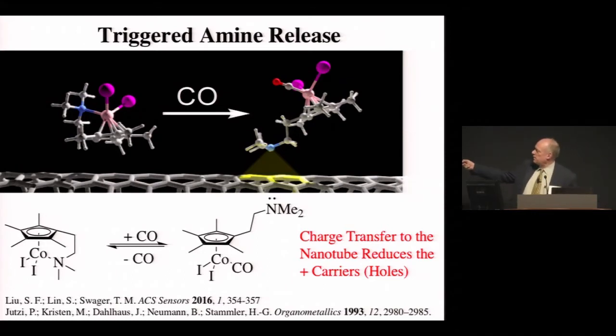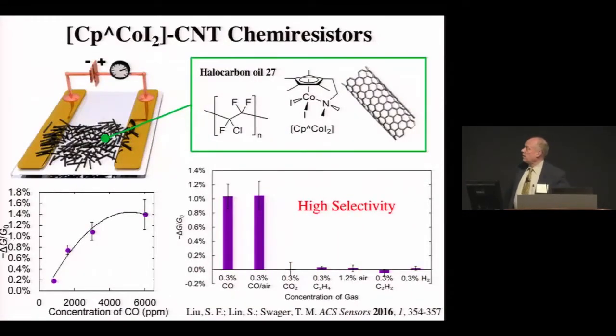And this is very nice because these amines have a lone pair of electrons, which is a good donor. And so when we have these cations in the nanotube, that amine essentially is like a little tractor beam, or it basically locks on them, donates electron density, and pins them, and also compensates for the charge and de-dopes the nanotubes. So we get a very big effect when you have amines that interact with carbon nanotubes.